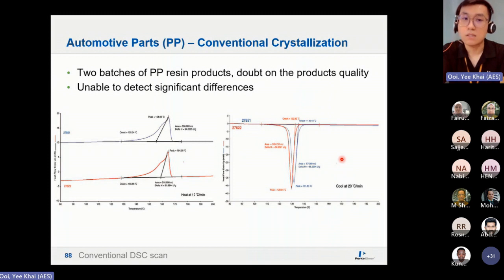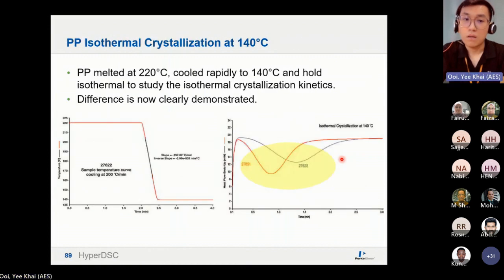But during the processes, they actually found that one batch contains issues. So what we did is we melted the materials at 220, and then after that cooled very, very rapidly back to 140 and held isothermal to monitor the crystallization kinetics.